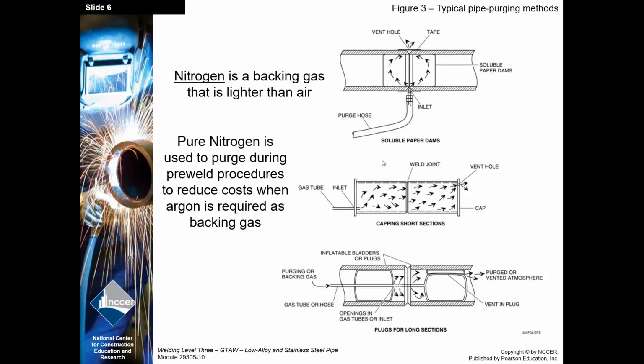We can do it several different ways. You could use bladders or plugs, pigs. At KWI, on your small coupons to practice, we're going to use masking tape. You're going to tape up the ends. You're going to tape up your root. You're going to stuff in a secondary hose, an argon hose, and then start flowing that argon in. Open your vent hole up on the top. You're going to leak it in the bottom. Argon's heavy, so it's going to build up and fill it up before it starts leaking out the top vent hole. Because now that's an inert environment in there, when you weld, that root will look pretty and slick, and it won't turn black and crystallize to sugar your root.